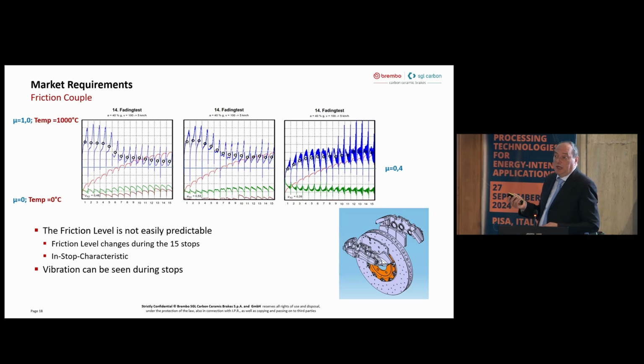Then, friction couple. What is important is that the brake system is not just the rotor. There are also pads and caliper. Especially the pads are really important, because here is an example: the same brake rotor and 3 different pads. You can see the behavior in a not so difficult type of brake, a fading test at 0.4 G. Normally you don't brake at 0.4 G, but it is like you have a panic stop. It's nothing for this type of rotor.